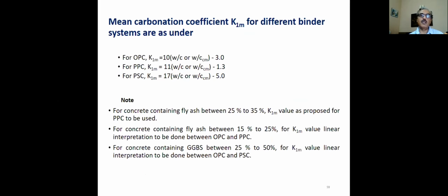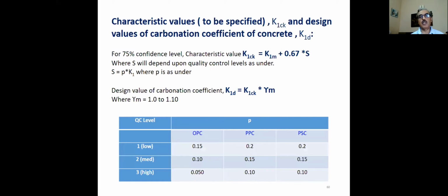Then these are the equations based on water cement ratios, from which we can assess the carbonation coefficient of different concretes - different for OPC, PPC, and PSC. And similarly for different amounts of fly ash added in OPC, we can work out the carbonation coefficients.